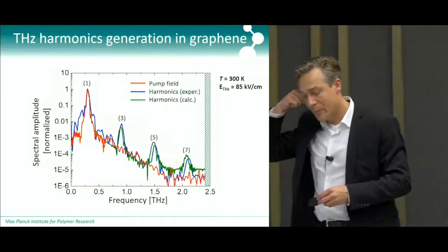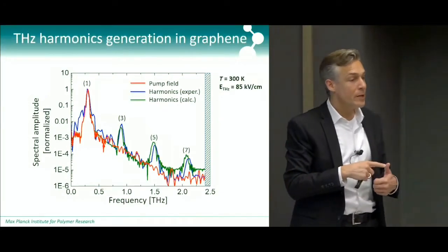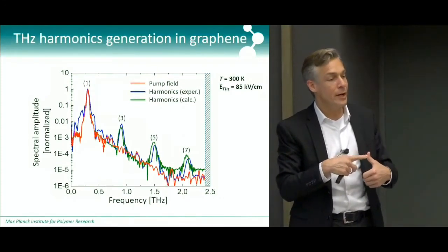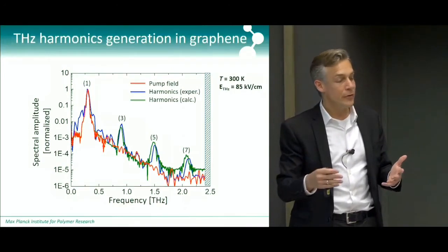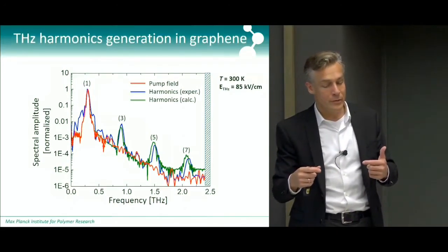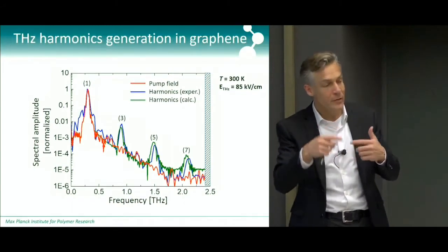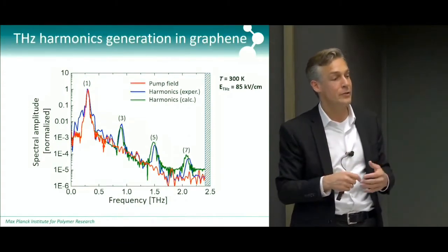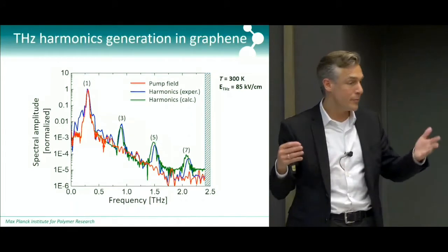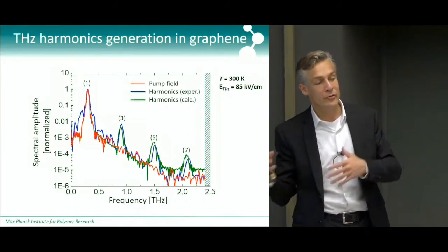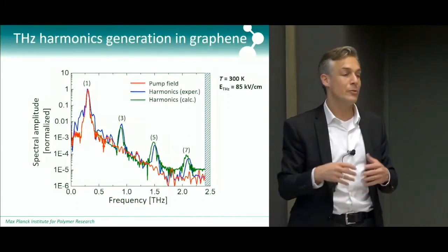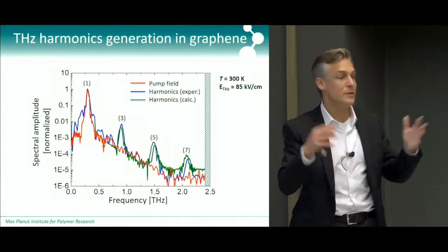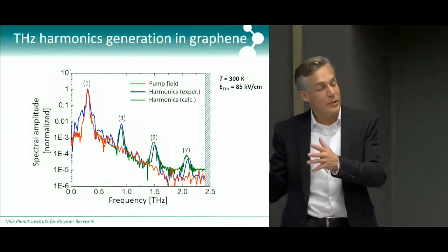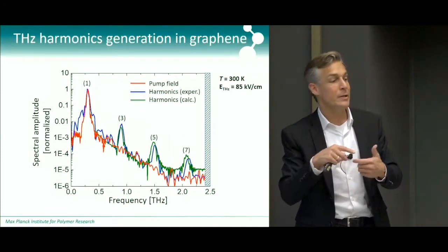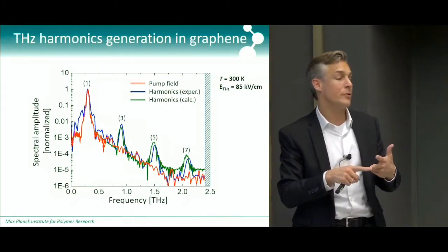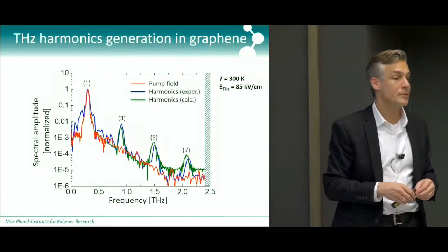So there's a couple of reasons. The mobility of graphene, the electron mobility of graphene, is very high, much higher than in most metals, and so the conversion of the field into heat essentially is very efficient, and is much more efficient than in a metal, which also has much stronger electron-phonon coupling than graphene. So you will very quickly also start emitting LO-phonons that will heat the whole lattice. So all these problems don't exist in graphene. So high mobility, high nonlinearity, and very little electron-phonon coupling. Those are, I think, the main effects.